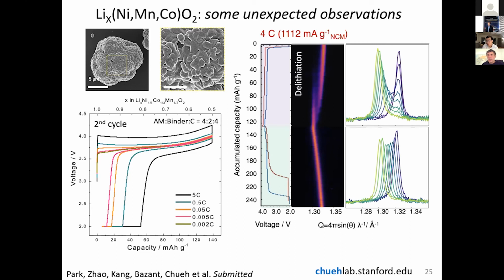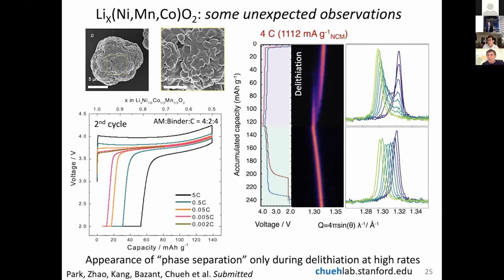But very interestingly, it only happens when you remove lithium, but it doesn't happen when you insert lithium, which is on the bottom of the plot. So this is something that's very interesting. It tells us that we have phase separation during delithiation and only at high rates.